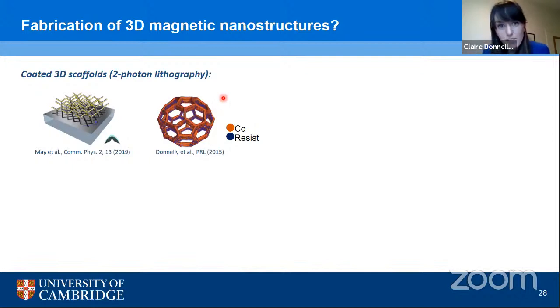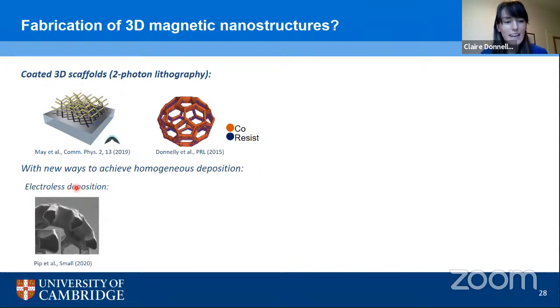Now, one of the main challenges here is the actual magnetic coating. So you can maybe note in this element-specific rendering of the buckyball here, where the cobalt is shown in orange and the polymer resist is shown in purple, that we can still see parts of the resist. And this indicates the significant shadowing effects that we actually get when we try to coat these 3D structures with traditional techniques such as sputtering or evaporation. And we've done quite a lot of work in the last few years to try and overcome these limitations and achieve a more homogeneous deposition onto these scaffolds. And one way in which we've done this is through the development of electroless deposition.